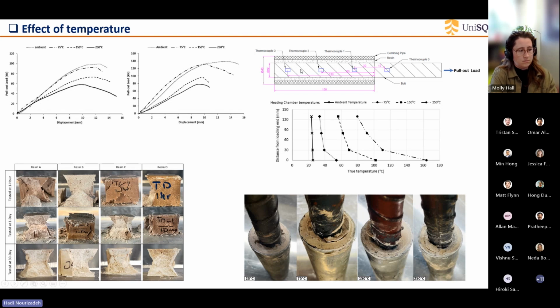in tunnels? So what we did, we cast some samples using different types of resins. I'm just going to focus on one type of resin. In this resin, we installed thermocouples at different distances. Then we carried out the pullout test again. We measured the temperature along the encapsulation lengths. As you see here, we have the ambient temperature of 75 degrees all the way to 250 degrees. We have different distributions of temperature along the encapsulation lengths.